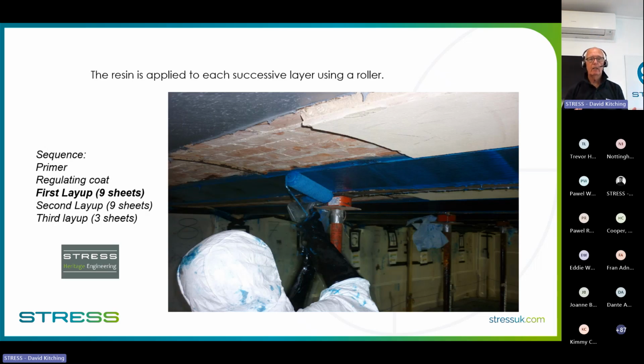Now you will see here that, in that list, we've got the first layup, which is 9 sheets. Now, I still don't know why, out of 21 total layers of carbon fiber we're going to put up, we didn't do 7, 7, and 7. But for some reason, it was 9, 9, and 3. I've absolutely got no idea why, and I don't know why I didn't ask the question at the time. But you put it up in a series of layers like that because, if you remember, the only layer that's in contact with the brickwork, which is the most important one, is that first layer.